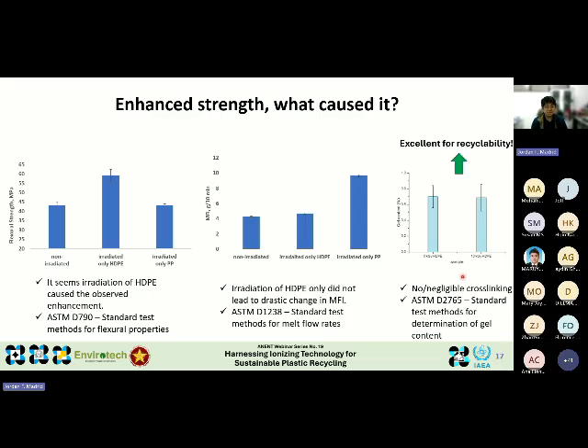This finding is very significant because we don't want our HDPE to cross-link, since cross-linked plastics are difficult, if not impossible, to recycle. Instead, what we hypothesize is that the radiation-induced branching in HDPE occurred during irradiation, and this branching likely improved the compatibility between HDPE and polypropylene, which could be one of the key reasons behind the enhanced flexural strength observed in the blends.